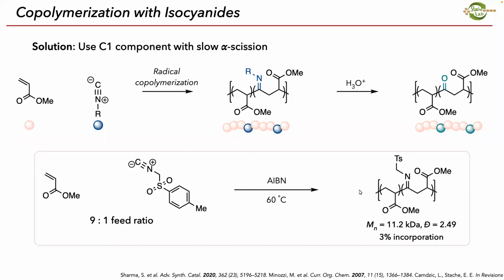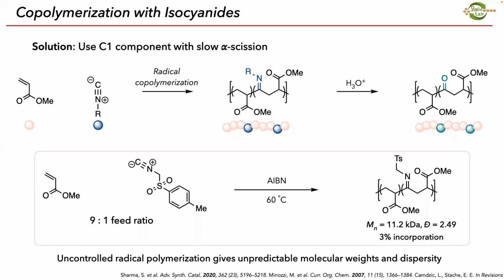There we go. Okay. So my student, Layla, is a third-year graduate student. She took methyl acrylate, which is a common monomer, polymerized it with this bench-stable isocyanide in a certain monomer ratio. And with AIBN, which is a very common radical initiator, she was able to see incorporation of that isocyanide in a non-alternating fashion. And we could tune this depending on how much of the isocyanide we use, with, however, uncontrolled molecular weight and broad dispersity. And I'll talk about what that means in just a second.